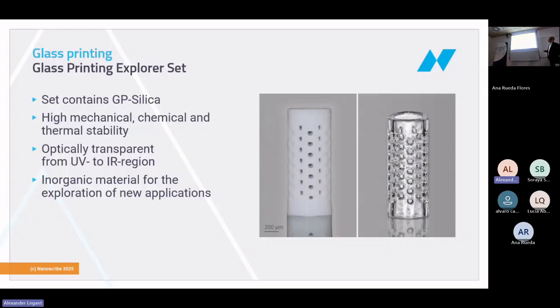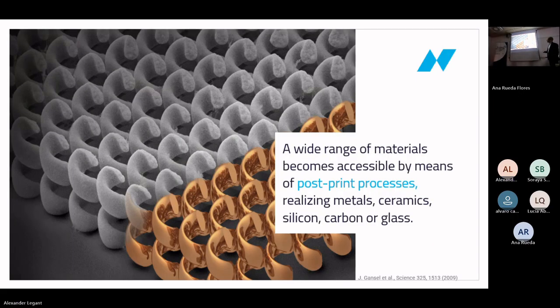More materials. As mentioned, I showed Glasomer before, so you can buy these types of print sets with silica nanoparticles inside. After two baking steps, you get, via the brown and green part from left to right, really fused silica glass. But from left to right, you also have shrinkage of 35%. That means typically you only do that for bigger structures, for medium-sized structures.